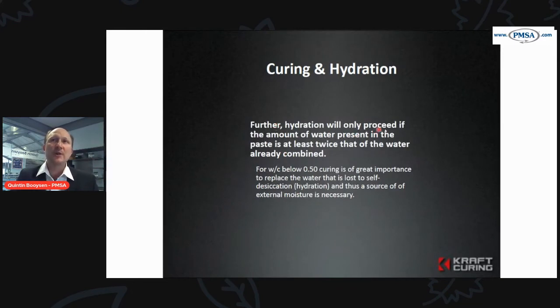Further, hydration will only proceed if the amount of water present in the paste is at least twice that of the water already combined. So this is critical when you have very dry concretes. Like in our industry, we work a lot with vibrated concrete in brick and block production, paving production, or even your hollow core slabs. And so we're not referring too much to your wet concretes, your high slump concretes here. Where your water cement ratio is below 0.5, it is of great importance to replace the water that is lost in the self-desiccation or the hydration, and thus a source of external moisture is necessary.